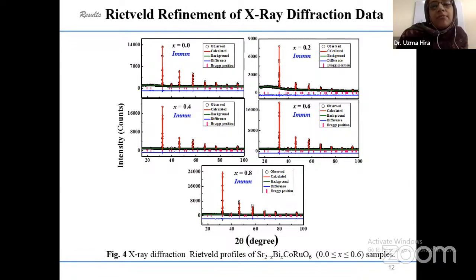These are the Rietveld refinement analyses of the XRD diffraction data, and you can see the nice fit of the model within this space group Immm, which indicates that our model is perfect and it is following this orthorhombic crystal structure symmetry.